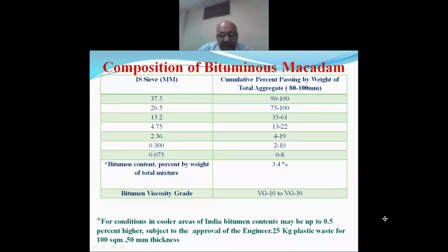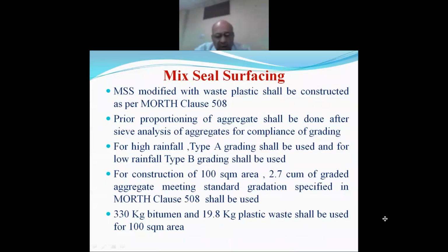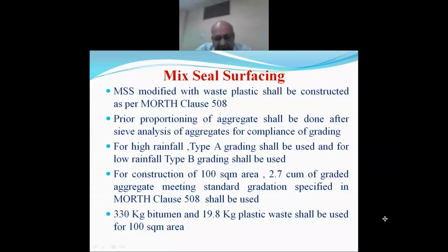Prior proportioning of the aggregate shall be done after sieve analysis of the aggregate for compliance of the grading. Plastic waste shall be 6% by weight of bitumen or 0.22% by weight of bituminous mixture. Mix can be prepared in a modified hot mix plant. For construction of 100 square meter area, grading given in MoRTH Clause 508 shall be applicable.